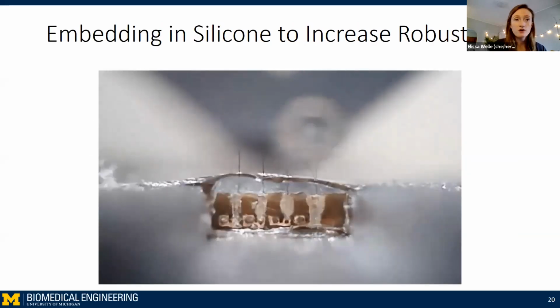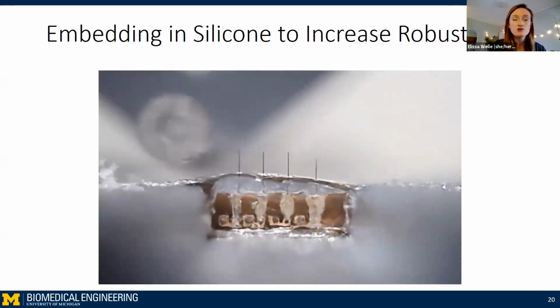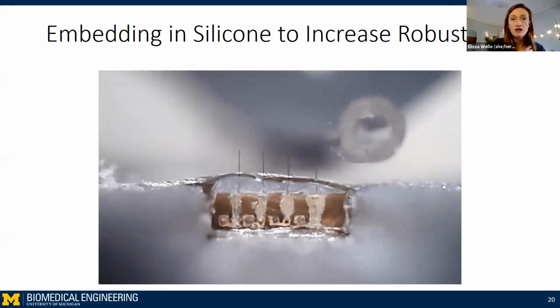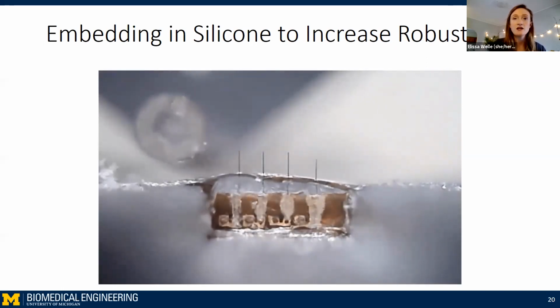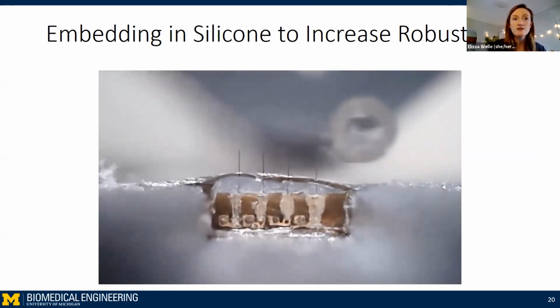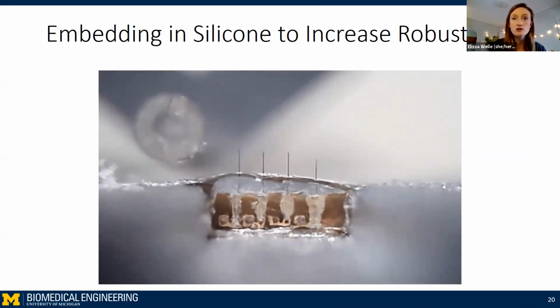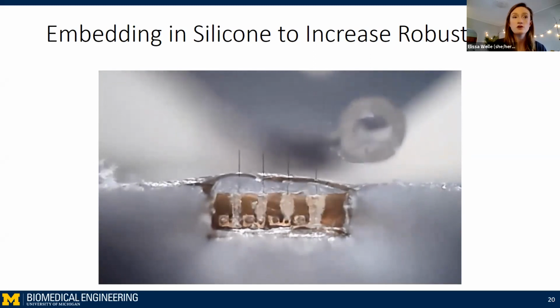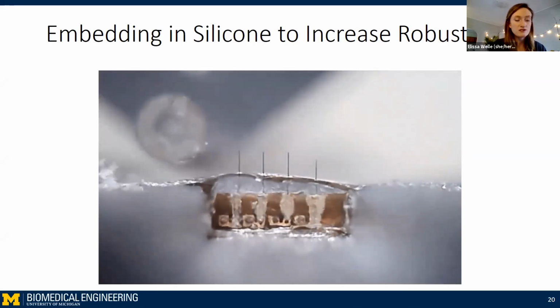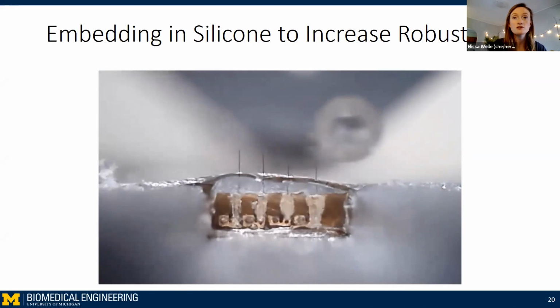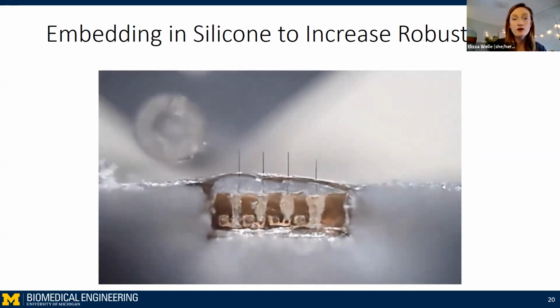So with all that, one of the next things was that the main limitation of the arrays that I showed you before is the fact that the fibers break really easily at the end of the printed circuit board. So to counter that, we embedded the fibers partially in silicone. And the silicone greatly increased the robustness of the carbon fibers. Here you can see a glass capillary running over the free end of the fibers without breaking.